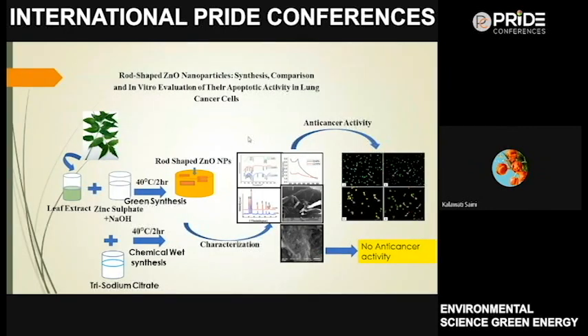This is the graphical representation of my comparative study of zinc oxide synthesized by the green method as well as by the chemical wet method. In green synthesis, we have taken 1 ml in one set of experiments, and in another set of experiments, we have taken 2 ml of leaf extract, 0.2 molar zinc sulfate, and 0.2 molar sodium hydroxide, and put it for 2 hours at 40 degrees centigrade on a hot magnetic stirrer. In this case, we obtained rod shaped zinc oxide nanoparticles. These are the FTIR, powder XRD, UV visible, and FESEM of these synthesized green particles.